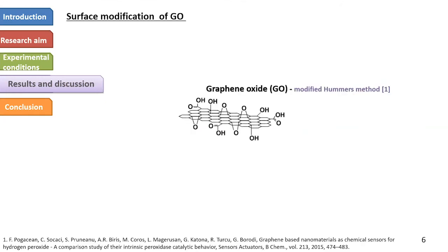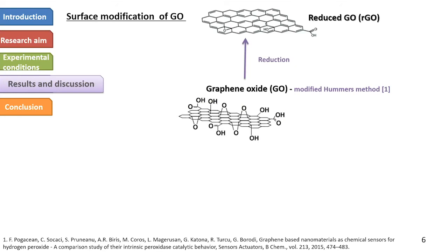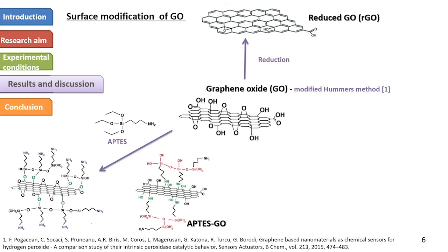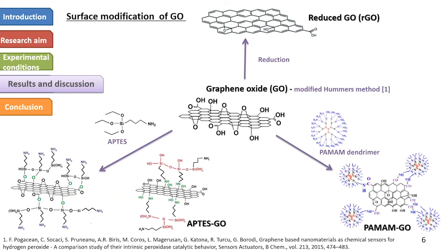So we work with 4 different graphenes, which will be presented in this slide. The graphene oxide, the reduced graphene oxide, then the APTES modified graphene oxide. Here we can see that the APTES molecule forms covalent bonds through the ethoxysilane groups with the hydroxyl of the GO releasing ethanol. It is also possible that the amine of the APTES reacts with the epoxy groups found on the surface of GO. And the last one, the PAMAM dendrimer forms covalent bonds through the amino groups with the carboxyl groups of GO. Here we can see the PAMAM modified graphene oxide. It is important that through chemical functionalization, we can also prevent the agglomeration of the graphenes.